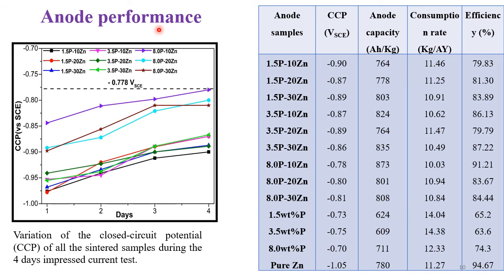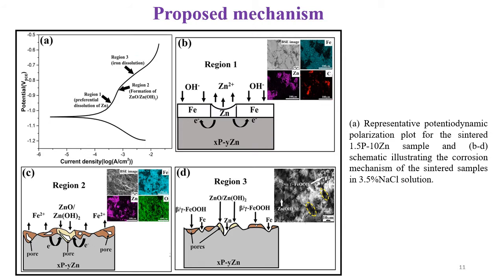And coming to the anodic performance which we obtained from the impressed current test, the closed circuit potential of all the sintered samples has been found to lie below the protective potential of steel, and the 1.5% composition shows comparatively more active closed circuit potential compared to the 3.5 and 8% compositions. The anode capacity and efficiency of all the sintered samples have been found to be above 750 and 80% respectively, which is comparable to that of pure zinc. Moreover, the anode capacity and efficiency of these hybrid anodes are much larger as compared to that of the previously developed HPPI anodes.